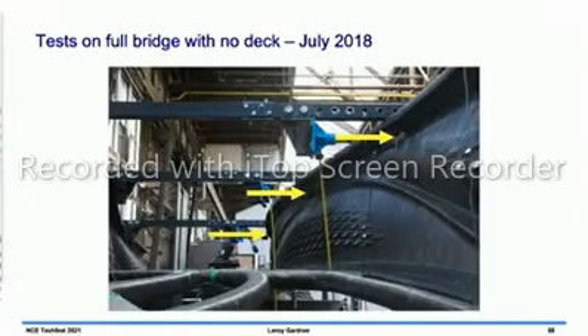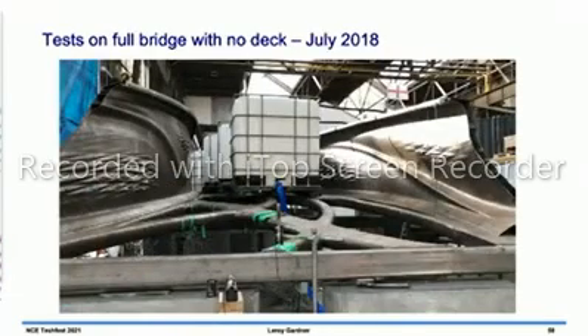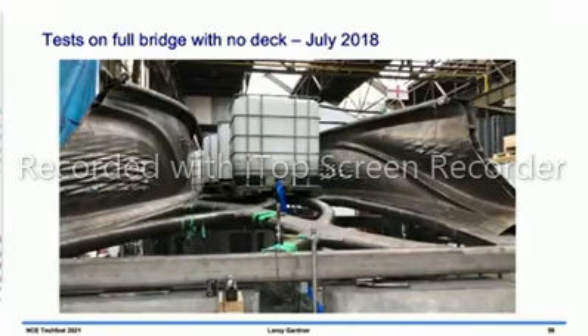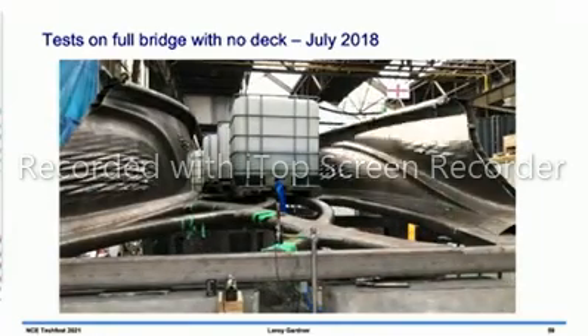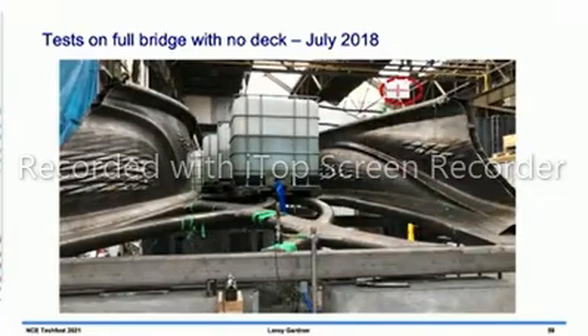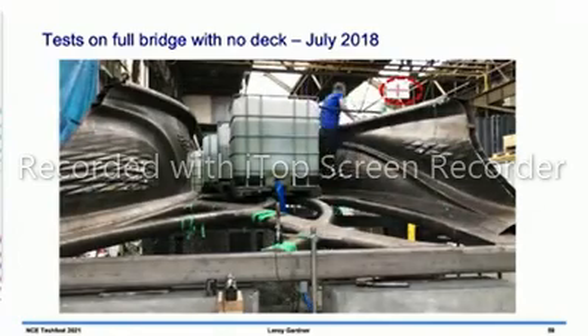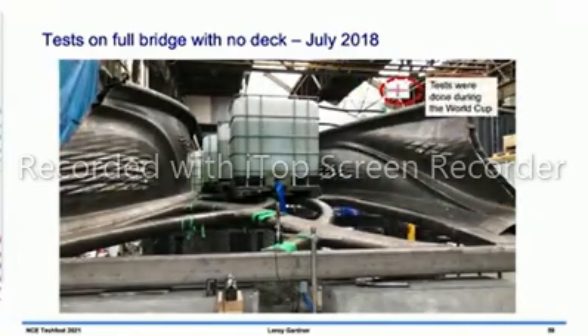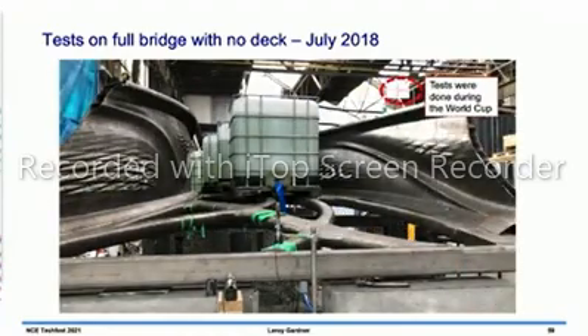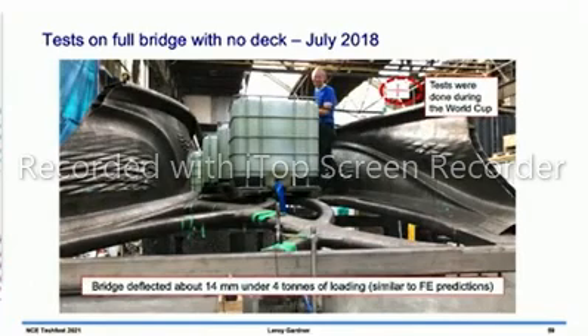2 main loading arrangements. So one was horizontal loading. We were pushing out on the handrails and pulling in on the handrails, simulating sort of crowds on the bridge. And then we had vertical loading. Initially, we put water tanks on the bridge, 1 meter cubed, filled them up with water, and that applied a total of 4 tons of loading. We got the England flag there. These tests were done during the World Cup in 2018. We were in the Netherlands. They hadn't qualified. We thought we'd just make our point. We did quite well. And the bridge deflected about 14 millimeters under this 4 tons of loading, and that was similar to our finite element model predictions, so that gave us a bit of confidence in the model.